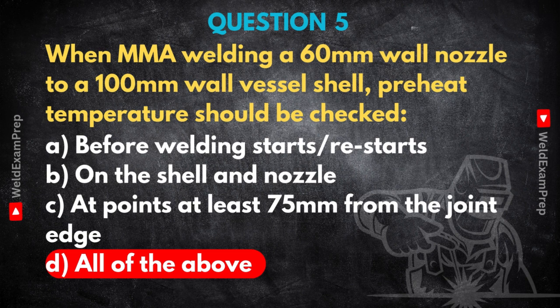Second, checking on both the shell and the nozzle. This is vital because you've got two components, maybe with different thicknesses, different thermal masses. They need to be heated uniformly. Uneven heating causes differential expansion and contraction, which can induce serious stresses. Got it. Uniformity across the joint.